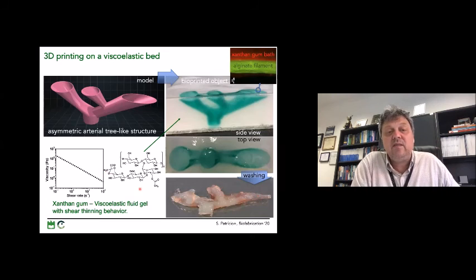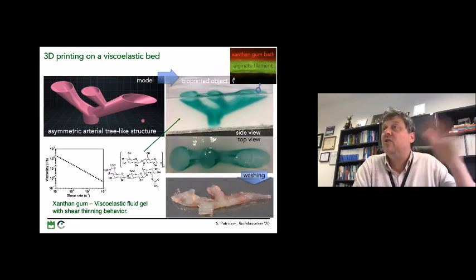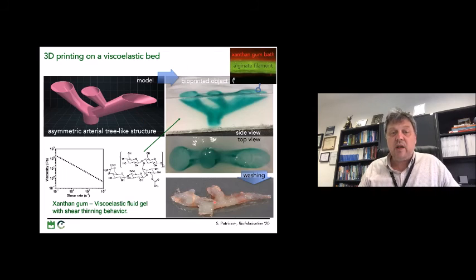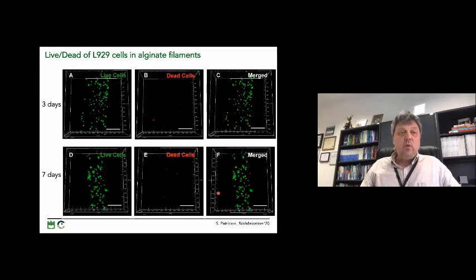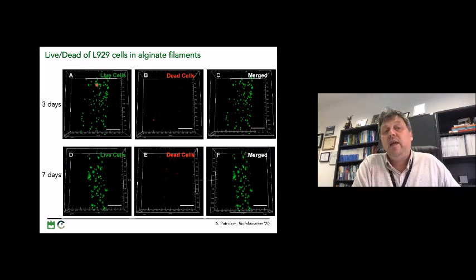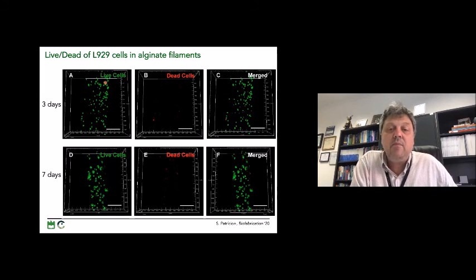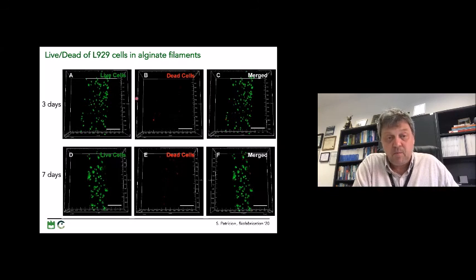So we could see that these kind of structures can then be isolated from the supporting bath because xanthan gum is water soluble. So we just wash with water and we can obtain the final structure. We could check that during printing of the alginate systems, cells could be included in the structures. They could be maintained in terms of viability. So this is really important to show that this kind of technology offers the unique possibility to really create volumetric out-of-space constructs with very high speed, which is also a very important property, and also with a very good printing fidelity, and also exhibit low cytotoxicity for cell bioprinting.